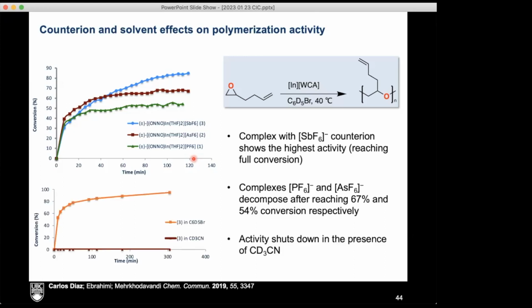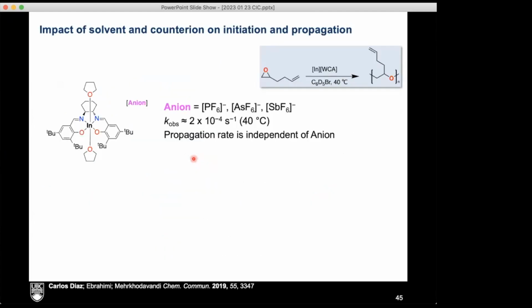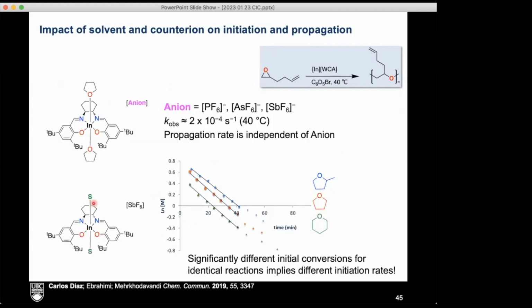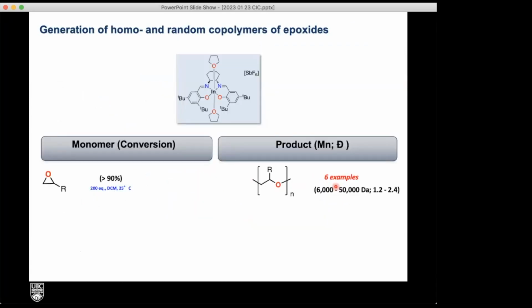And he also showed that it's very much solvent dependent. So if the solvent is a donor solvent, it shuts down the reaction. And this has to do with the fact that it matters what these solvents are in the axial position. If he has a really good donor, it changes the reactivity. So if he has a solvent molecule that will dissociate faster, the reaction goes faster. If one coordinates stronger, the reaction is slower. So that made sense.